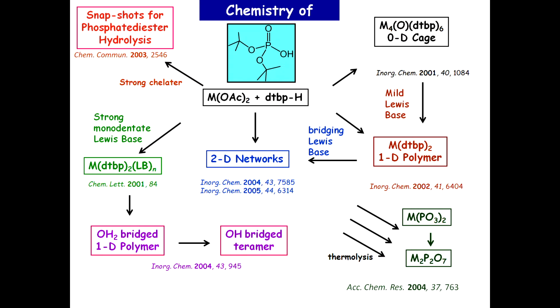Everything else is inorganic. So, as a result, if you start heating all these molecules shown in the left and left top part of the transparency to about 150 to 200 degrees centigrade, they will lose the tertiary butyl group as isobutene and produce the corresponding hydrogen phosphates, which go on to self-condense to form either pyrophosphates or metaphosphates, depending on the composition you start with.